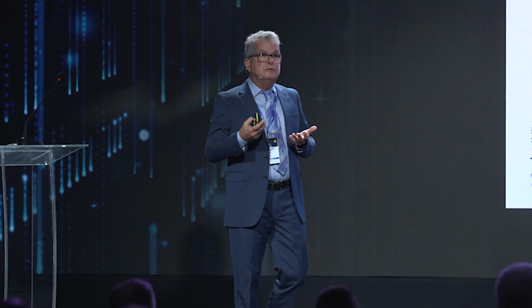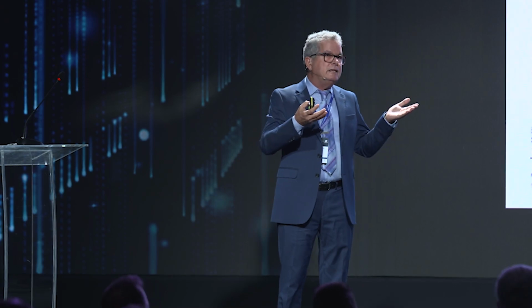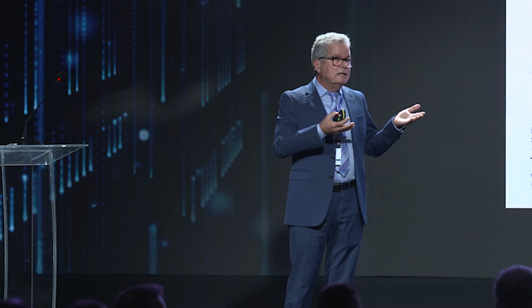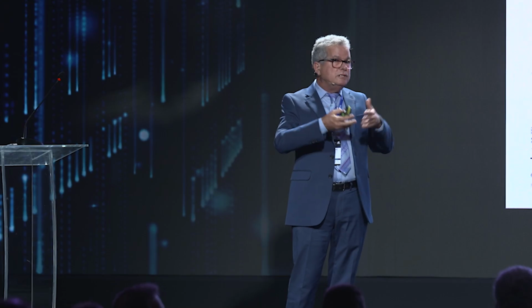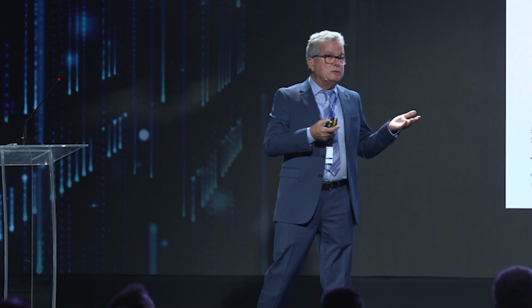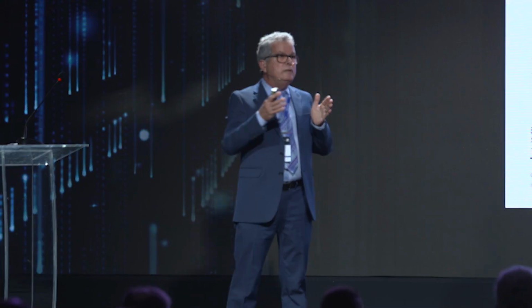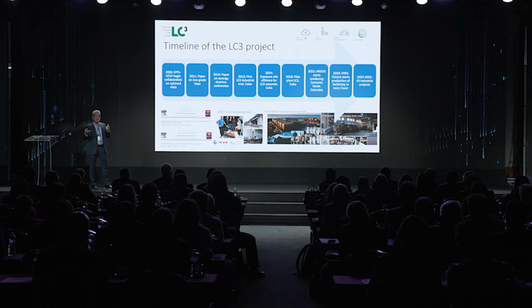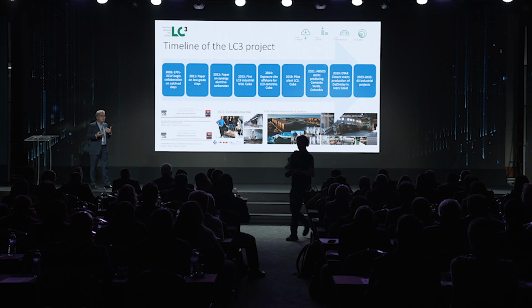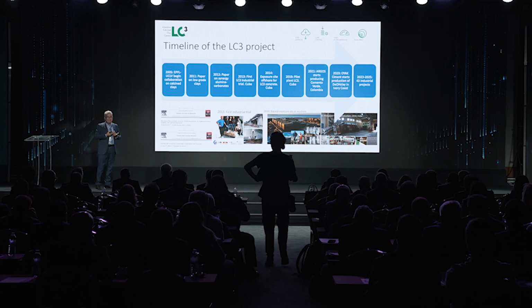The original idea was, instead of making a high purity metakaolin, to use a low-grade clay, a clay with a lower kaolinite content, which is widely abundant in the world, as a normal pozzolan. But then, while we were doing the research on this material, we realized that through the combination of calcined clays with limestone, there was a synergy. And the synergy was the reason to form new hydration products, alumina-based hydration products, and that was the base also for increasing the clinker substitution rate. And this is how we came across the concept of the LC3. This happened in 2009, more or less.